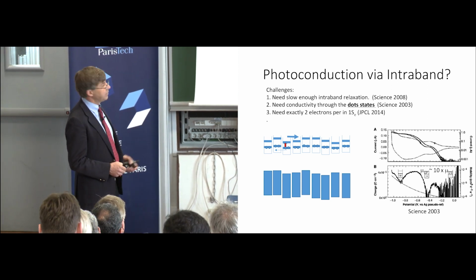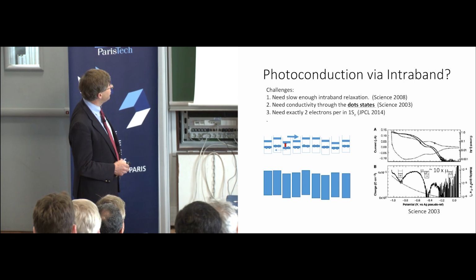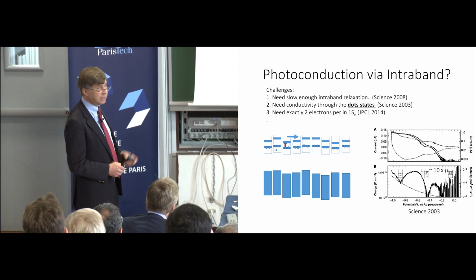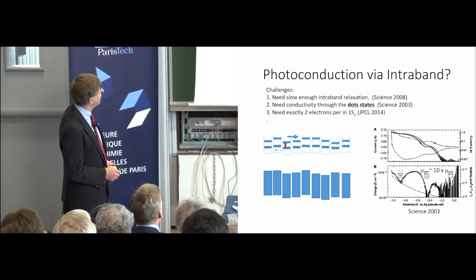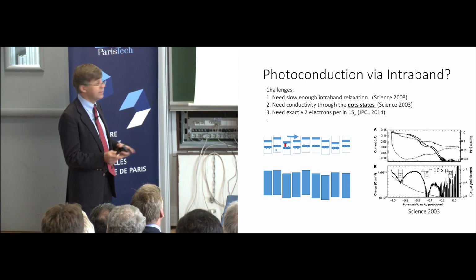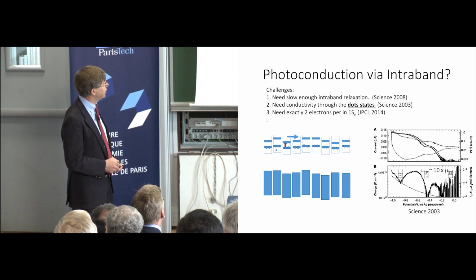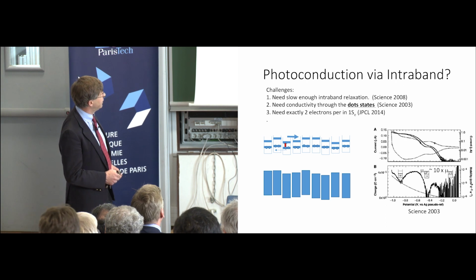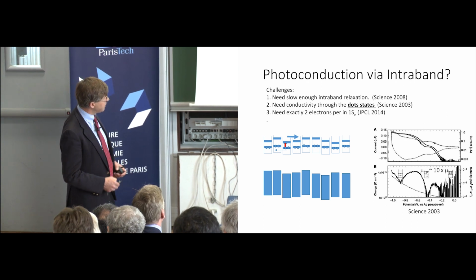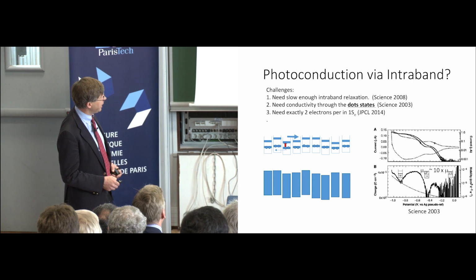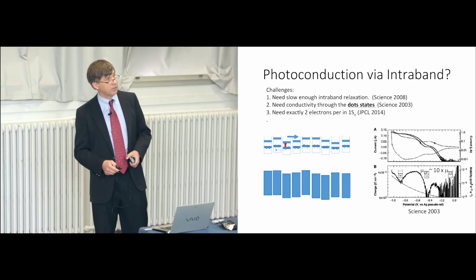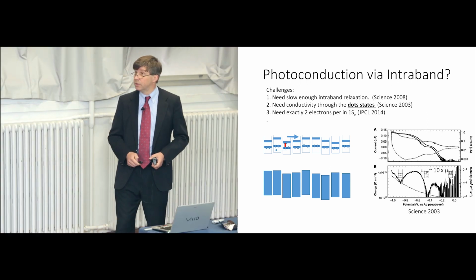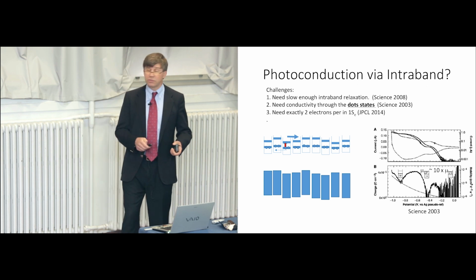The dots are not the same size. It's highly disordered. We need to have exactly 2 electrons per dot, so we have a nice conductivity minimum. We need to have the electrons easily go from dot to dot, so there was a lot of things to solve. One thing that was promising was back in Science 2003, we showed that the mobility of the electrons in the p state was about 10 times larger than the mobility of electron in the s state. So there is some hope.